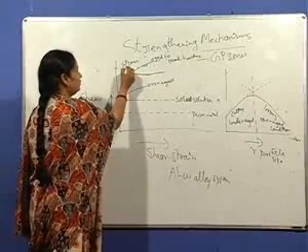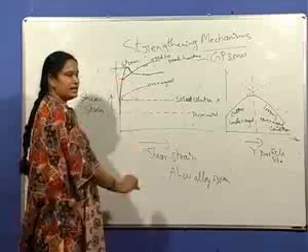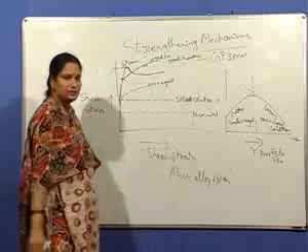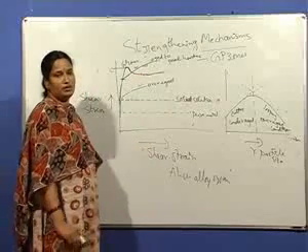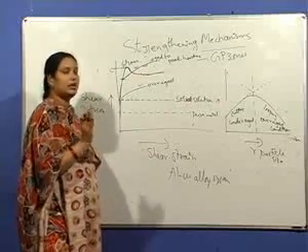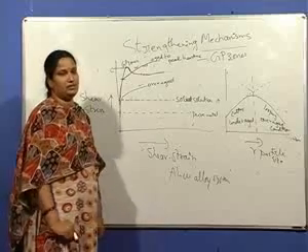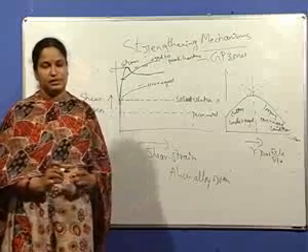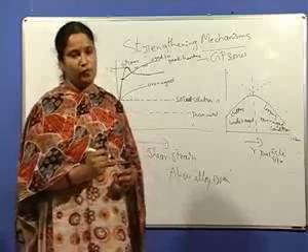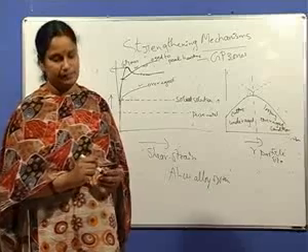So for the case of cutting mechanism, yield strength is higher, rate of strain hardening is lower. And for the case of looping mechanism, the yield strength is lower, but the rate of strain hardening is higher. So this is about the stress strain curves for the different phases of aluminum copper alloy system.